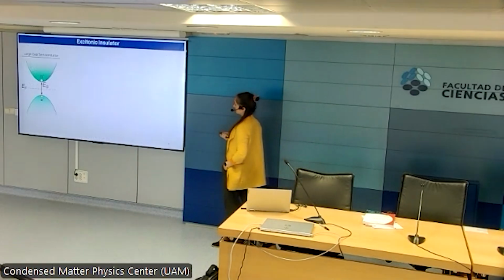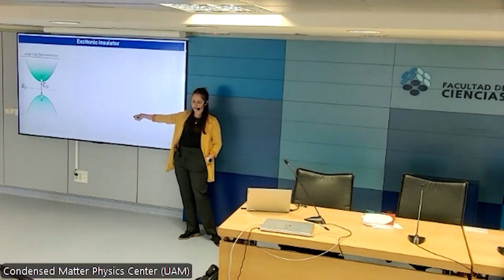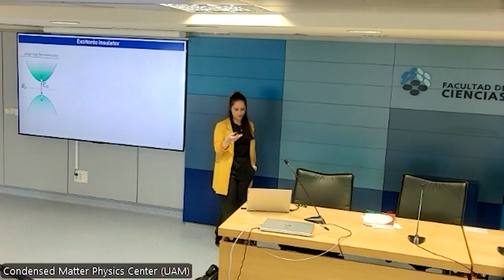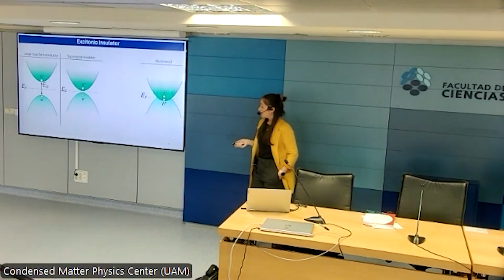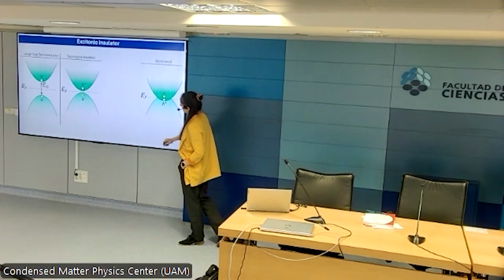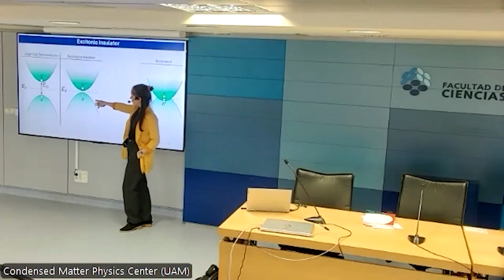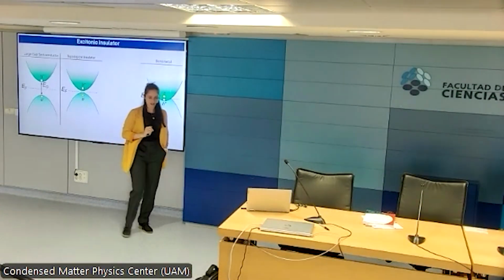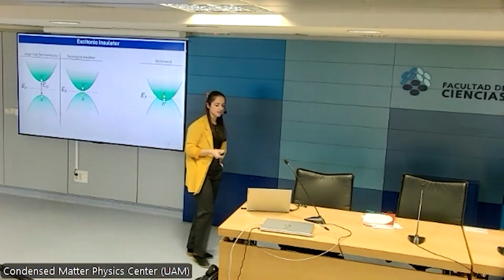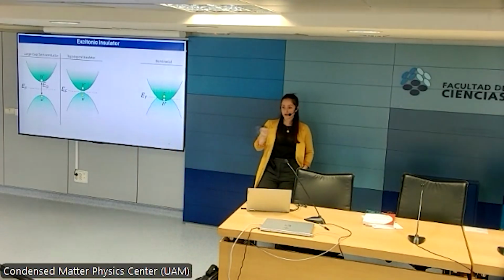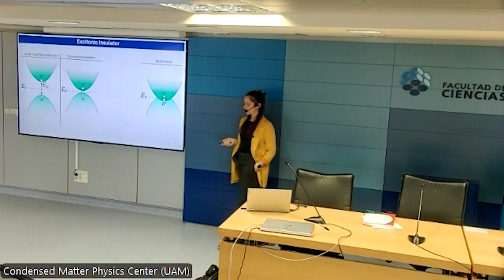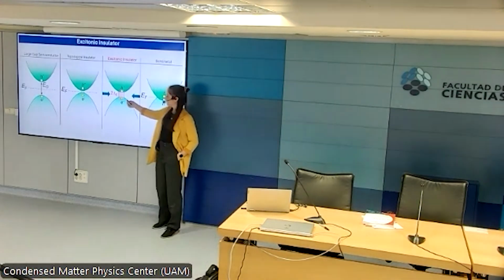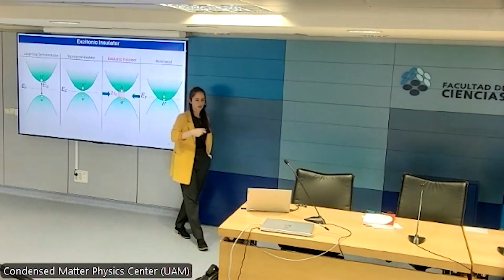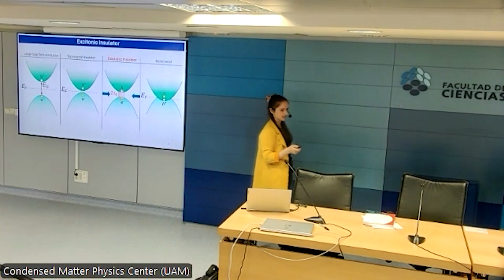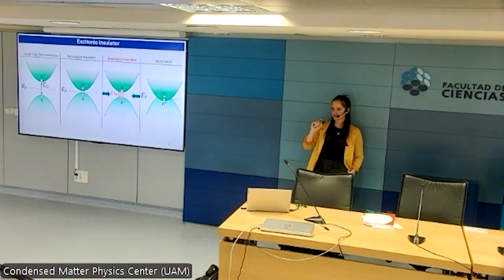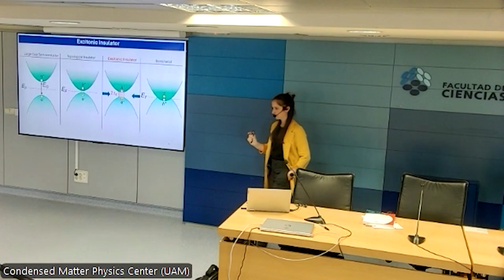In your normal material, in your large gap semiconductor, you have your valence band, your conduction band, electrons and holes, the pairs, we're all happy. In materials where the band gap is very small or non-existing, so for example, in the case of a topological insulator, here the dotted lines mark the edge states, or in the case of a metal, you can have the formation of excitons whose binding energy is actually larger than the band gap existing in the material. So you end up with a band gap that is not given by the fact that there are no available states in the Hamiltonian, but just given by the fact that electrons and holes pair together strongly, that there's no conductivity there.